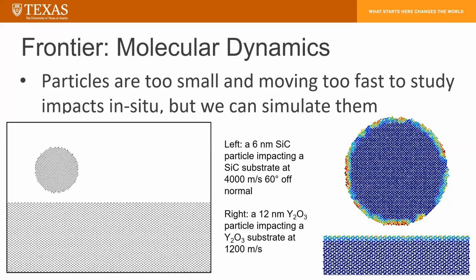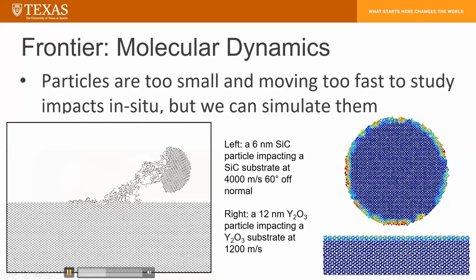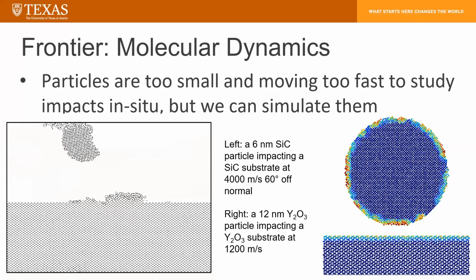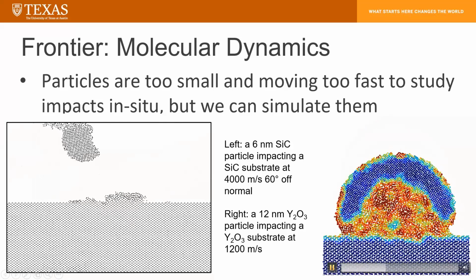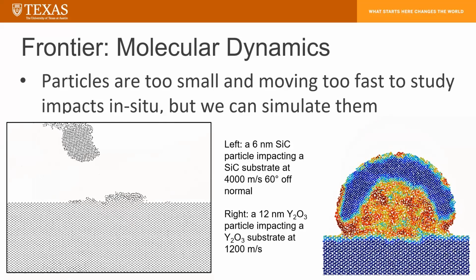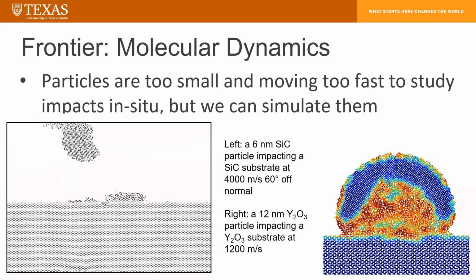So what we do is we actually simulate them atom by atom in a scale model through a process called molecular dynamics. Here are 2 results. One of these on the left is a silicon carbide particle hitting a silicon carbide substrate. And we can see that it's impacting at an angle, and the angle actually prevents it from adhering well. On the right, in contrast, we see yttria impacting yttria at a much lower velocity, but it does adhere. And so what we use molecular dynamics for is predicting what kind of regime we actually see adhesion and the deformation behaviors that we want to use to get our final film properties.